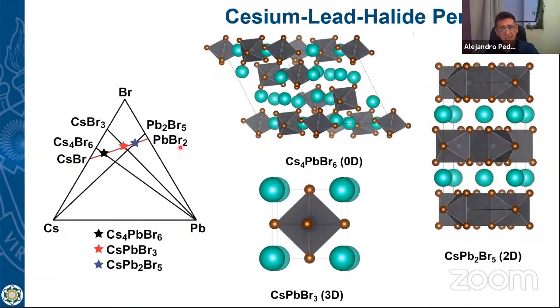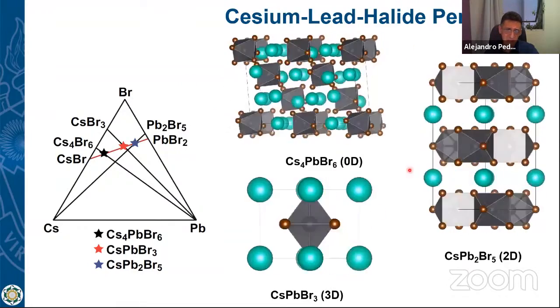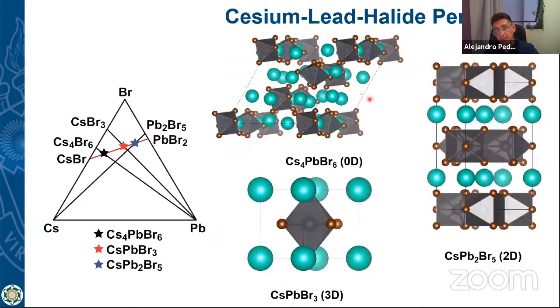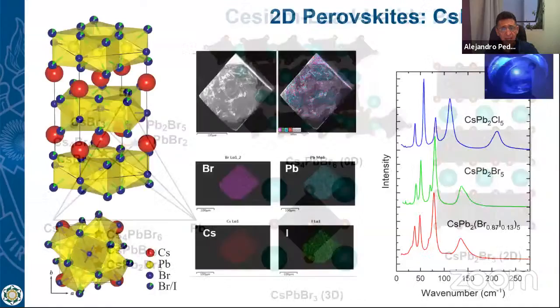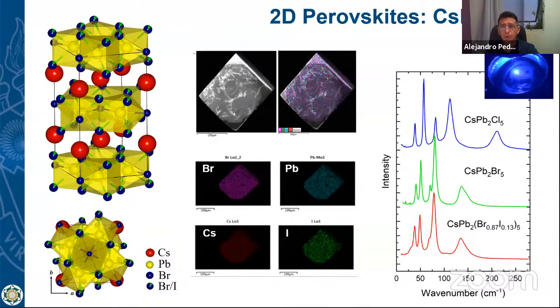So quickly, just a last example, we have been working on these materials which have this phase diagram, but I will discuss quickly this one, which is a cesium lead bromide or iodide. In fact, we were able to do some doping of the bromine with iodine, and you can see here first that with chlorine this band is at a high wave number. But remember, in the harmonic oscillator, the frequency of the oscillator is inversely proportional to the mass. When you increase the mass, the frequency is reduced. Since frequency is proportional to energy or wave number, the wave number is reduced. When you increase even more, introducing iodine, it is reduced even more.